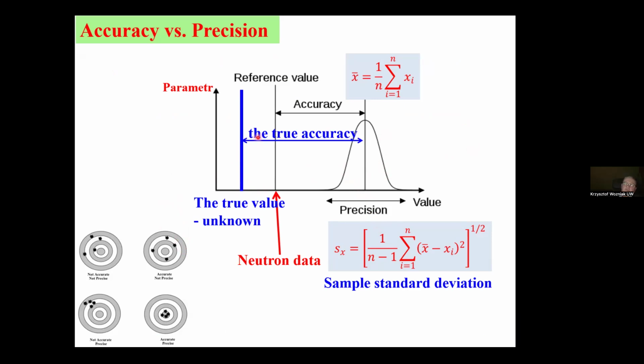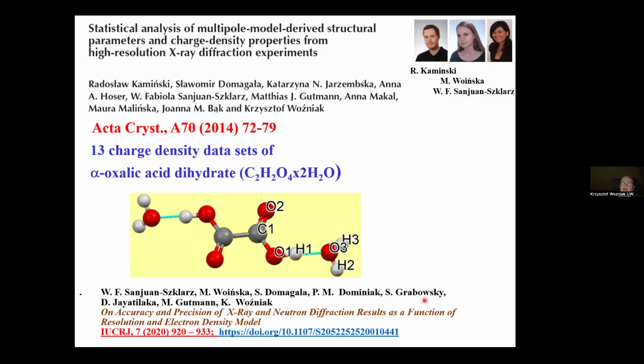But in the case of, for example, bonds to hydrogen atoms, we know that neutron data will be giving values closer to the true values than X-ray data. So we can have a relative accuracy as a difference between, say, if we collect multiple data sets, average values from X-ray diffraction and those from neutron diffraction. And of course, when we get multiple measurements, we can have an estimation of precision by using sample standard deviation. And that's what we did. We got 13 charge density data sets for hydrated oxalic acid, and that was a part of the PhD thesis of Radek Kamiński.